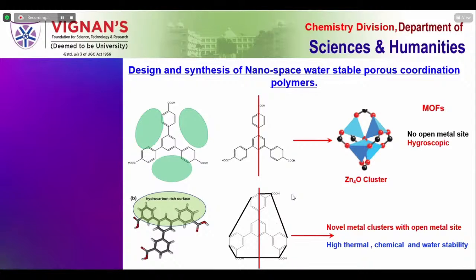We put those things in and dissolve them in a mixture of the solvents DMF, methanol, and water. Then we close the cap and heat hydrothermally in a furnace at about 100 degrees over 4 days. Then we got very beautiful crystals, as I showed you here. These are very beautiful crystals, and of course, the crystals were also solved by single crystal X-ray study.